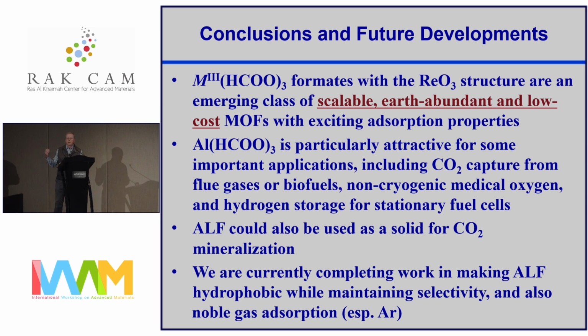And the reason the previous people never succeeded in activating it is that they tried to do it with the iron compound, the pure iron compound, and it's not as stable, and so they failed and they gave up on it. But aluminum is more stable, and there are lots of interesting possible applications, which I've talked about.